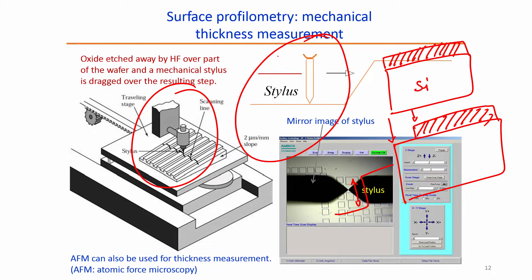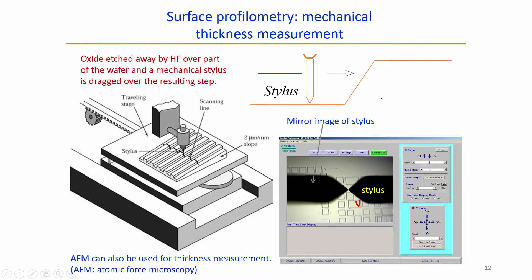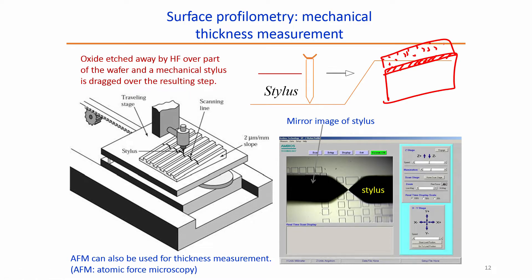What is the disadvantage of this particular system? The disadvantage is that we need to destruct the silicon or the layer that we have deposited onto the substrate. That means I have silicon dioxide everywhere, but in this case I have to pattern it so as to get the height of the material deposited onto the silicon wafer. These are destructive techniques because we cannot keep our film intact. For example, if I have an oxidized silicon wafer with aluminum everywhere, I want to know what is the thickness of this aluminum. I can only know when I create a step.